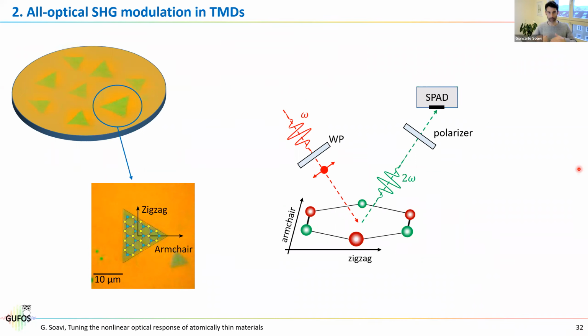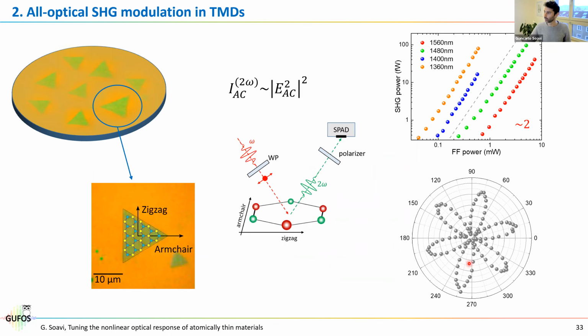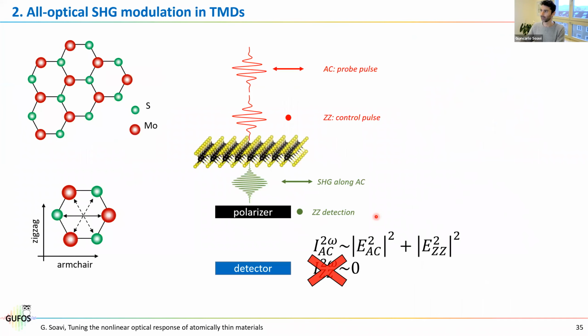However, to make sure that you are perfectly aligned, we first do a polarization dependent experiment. So basically we rotate the incoming polarization and we rotate also the detection polarization. And by doing that, we obtain this very nice six-fold pattern. And we know that each of these lobes is one of the armchair directions. So we know exactly what is the armchair in our material. We also do power dependent experiments and we see a slope of 2. So we know that we are really doing the second harmonic.